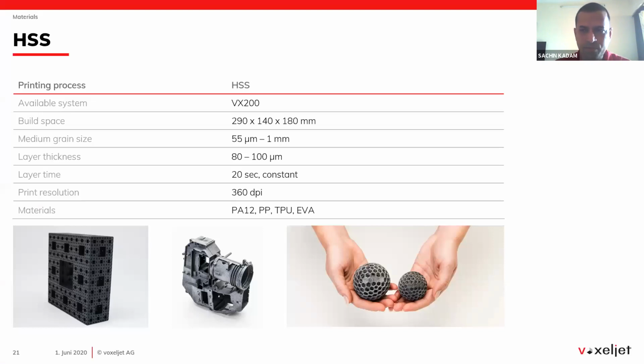So you have seen with this process we can produce a fabric kind of material also, which is very flexible. It is also possible to print different degrees of hardness with different ink inputs. Right now we have this process available with the VX200 system, which is the smallest system we have, with a size of 290 by 140 by 180 mm. So you can print 9 liters of volume. The grain size for this process varies from 55 micron to 1 mm. The layer thickness is basically 80 to 100 micron.